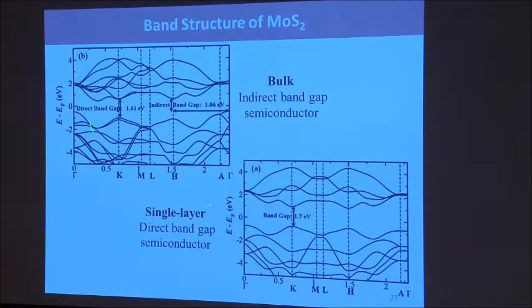This is a calculated structure. Bulk MoS2 has an indirect band gap, and as soon as you make a single layer, it becomes a direct band gap semiconductor with a band gap of 1.7 eV. These are some of the interesting things that were done a few years ago, three to four years ago, and many other things.